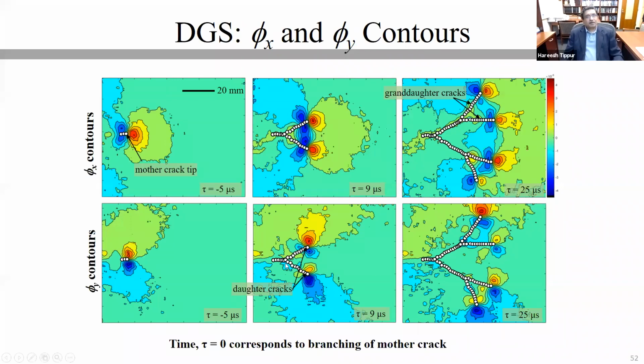Here are some still images from that experiment. The first column here represents Phi-X and Phi-Y contours for the mother crack, and the middle column for the daughter cracks. Once again, you see the one on the top is your Phi-X contours, gradients in the horizontal direction. And the bottom row represents contours corresponding to the vertical direction. The last column here is for the 4 granddaughter cracks, where you have the crack tip field surrounding each one of them. I like to plot these things in the form of contours because I came from interferometry, but in reality, this is information that is available everywhere in the field at the center of each subimage.